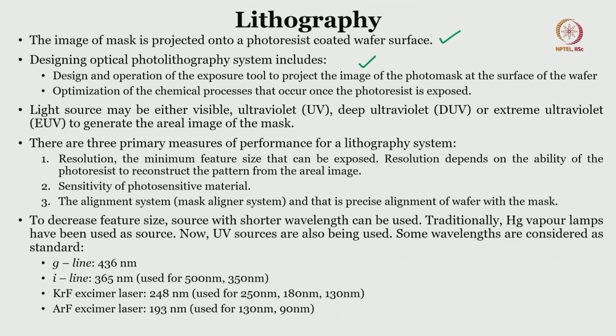There are three primary measures of performance for a lithography system. The first one is resolution, the minimum feature size. If you want to go for a feature size which is really less than 2 micrometer, somewhere in nanometer, you go for e-beam lithography. Otherwise above 2 micrometer, generally photolithography, UV lithography can be used. Again, ideally it depends on the wavelength of the light that we are using for exposing the material.